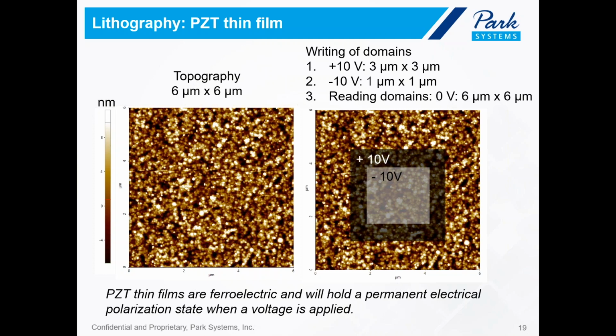So eventually, we will have 3 different domains. One being the unbiased one, which is the 6 micron by 6 micron area, and a section of positively biased, that's the 3 micron by 3 micron region, and a section that is negatively biased, that's the smallest 1 micron by 1 micron region. And then we will check the PFM phase to see if we can identify those different electrical polarization domains.